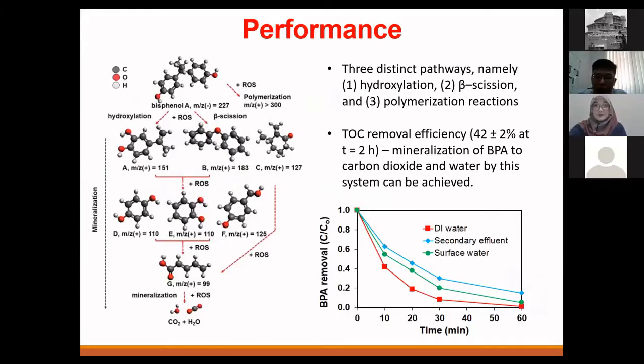So we test using DI water. We also use secondary effluent, that means the effluent from the wastewater treatment plant, and also surface water. That means we go to the river to collect the water. That's considered as surface water. Okay? And we found that, of course, in DI water you have the best performance. But when you use secondary effluent, you have a decrease of performance, not significantly, just a small decrease. I consider this as a minor decrease.